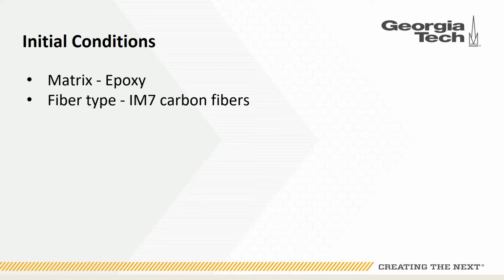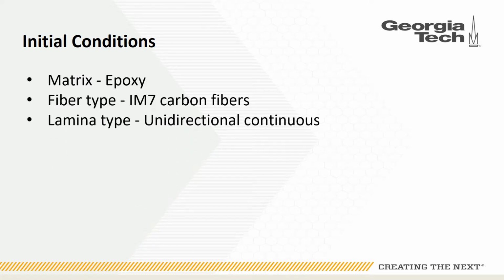And we chose carbon fibers over aramid fibers. Even though aramid fibers offered slightly higher strengths, their costs were exponentially more, so we decided to go with carbon fibers. As for IM7, we chose this because it was the most used carbon fiber in the aerospace industry, as well as having ample testing. For the lamina type, we chose unidirectional continuous. This is because they are the strongest type of lamina, as opposed to unidirectional discontinuous and random.